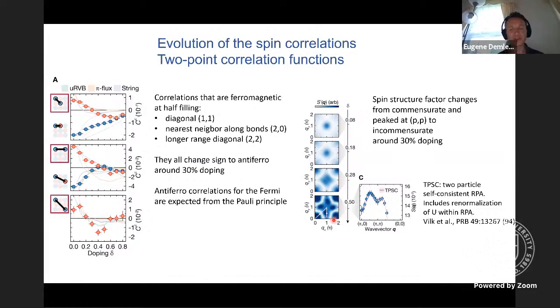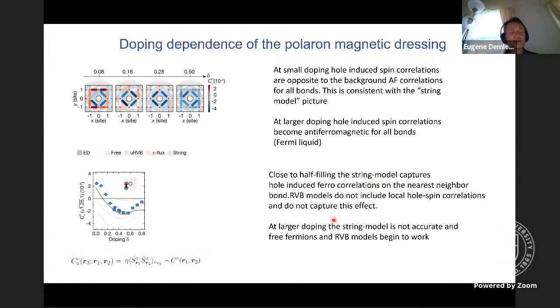Okay, but these are two-point correlation functions. Actually, you can look at three-point correlation functions. In this case, one takes a hole and looks at spin correlations in the vicinity of the hole. So these are really spin correlations conditioned on being close to a hole. It's really polaron correlations. Again, we see a dramatic evolution.